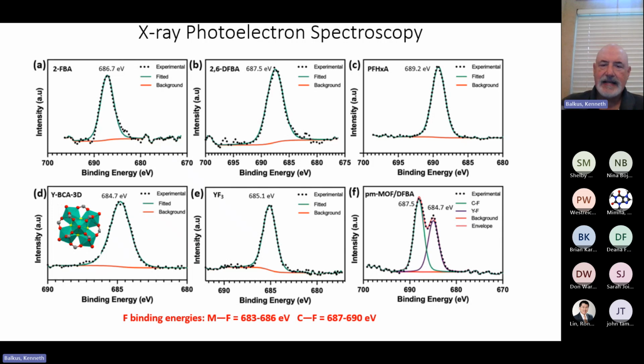So you can easily tell the difference between a metal fluorine bond and organofluorine. That ruled out the possibility that we're encapsulating or absorbing the organofluorine compound, because there's no evidence of that. But we definitely have metal fluorine bonds. And this one on the far right just shows you that you can resolve these two peaks very easily and see the difference between organofluorine versus metal fluorine.